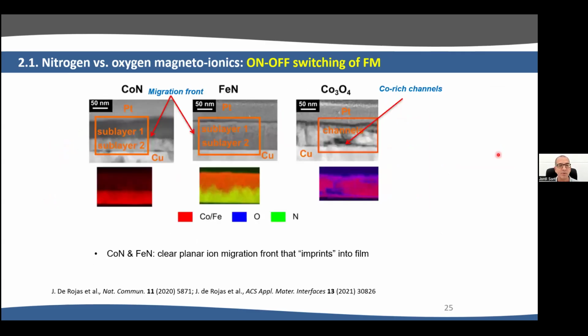Okay, next, what we did is to check also compositionally what happens in cobalt nitride, and also we tried with iron nitride. And we saw an interesting effect that I will expand a bit later, which is this planar front. So we start with this layer that at the beginning is homogeneous, and after treating with voltage, we subdivide the material into two regions, one of them that is more nitrogen than the other.